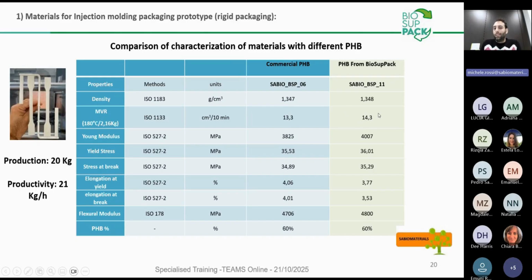14.3, so more or less the same value, and also the rigidity could be maintained as the same number. As you can see here, the number is more or less the same. We lost something in elongation. This is probably due to the fact that the polymers that we have obtained in the project present a different molecular weight compared to the commercial one. But in any case, all the material properties that we have detected from the Young modulus, the stress at break, and also the flexural modulus, for us represent a good starting point to say that the material obtained inside of BioSupPack is very similar to the PHB